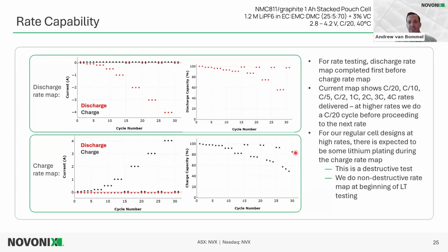So this indicates that there's potentially, if we took apart the cell, which we do often, we'd expect to see lithium plating for these cells. This is a loss of capacity during this testing. So this is why it's a destructive test. These cells can't go on to UHPC testing or long-term testing. They'd just be discarded.